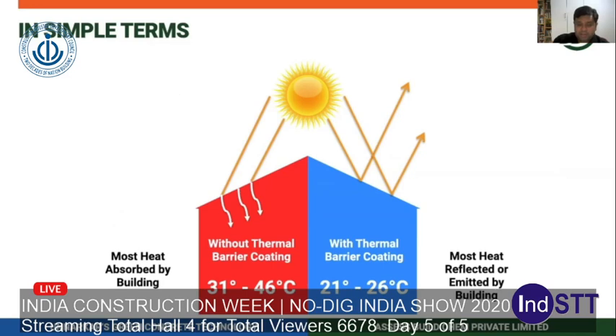In simple terms, if you're looking at a structure without thermal barrier coating, the temperatures normally seen are say about 31 to 46 degrees depending on summer and winter variations, and most of the heat is absorbed by the building. But if you're using a thermal barrier coating, most of the heat is reflected and emitted by the coating itself, and it allows very little heat to permeate through the building, in which case temperatures in practice were seen down to 21 to 26 degrees depending on seasonal variation.